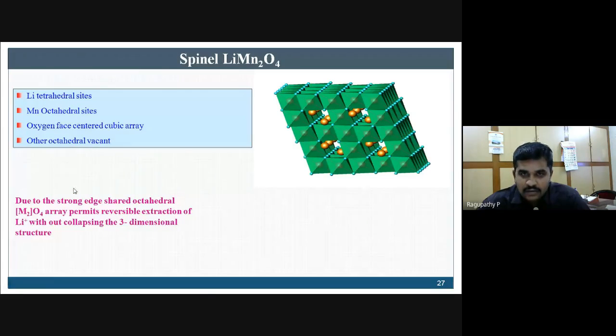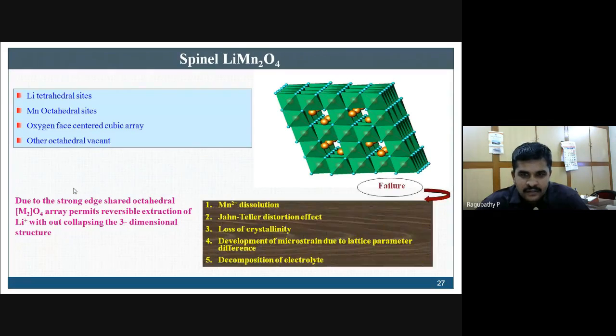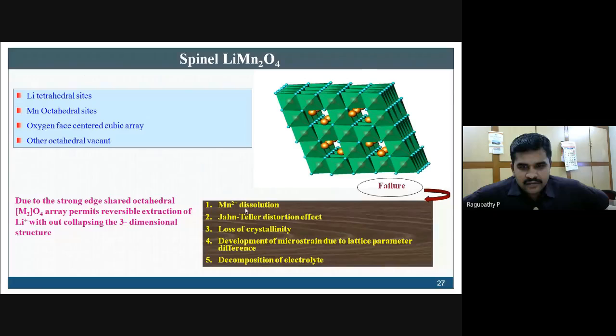Basically this is called the spinel lithium manganese oxide. Due to its structural feature, it gives a strong edge-sharing octahedral arrangement, which permits a reversible extraction of lithium without disturbing the structure. Then what is the problem? There are a lot of issues in this: the metal dissolution, manganese dissolution, and Jahn-Teller distortion, which is an effect in coordination compounds. And of course you have loss of crystallinity, development of microstrain, and a possibility of decomposition of the electrolyte. So these are the failures.